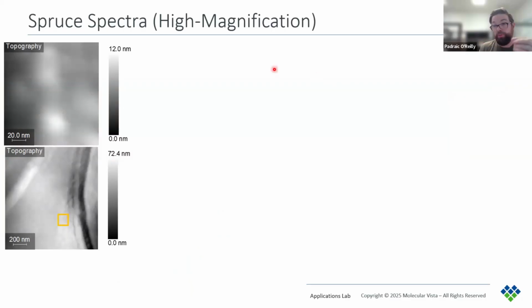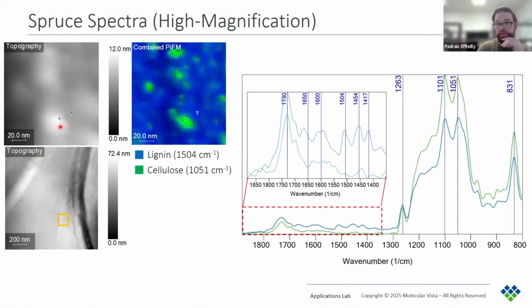Now, when we zoom in and take a topography image, there is some evidence of these sort of bumps on the surface. So these are going to be lighter in color, which represent taller in topography. Now, our chemical maps on this show that these bumps that are in the topography are cellulose, while the surrounding area in blue here is lignin. Now, there's actually also very small cellulose areas in the chemical map, so these green guys here, that cannot be discerned from the topography alone.